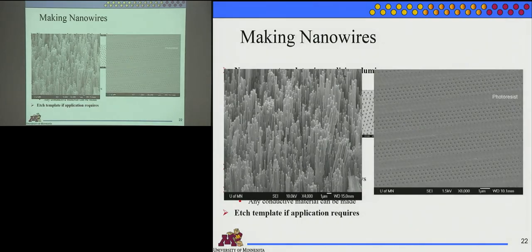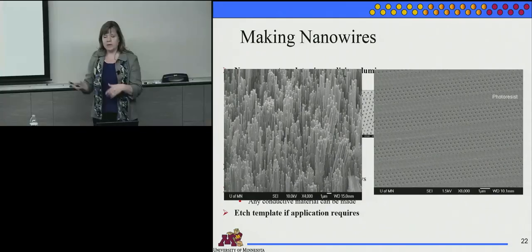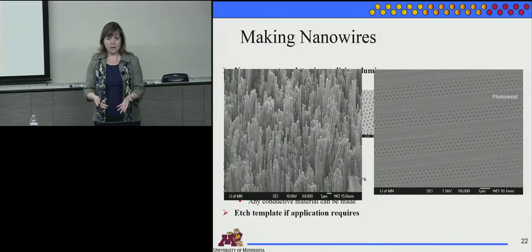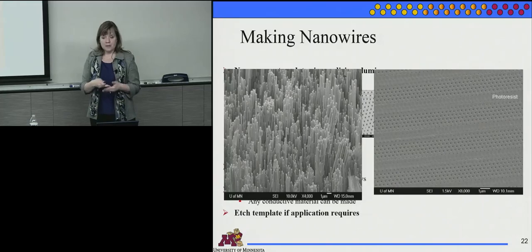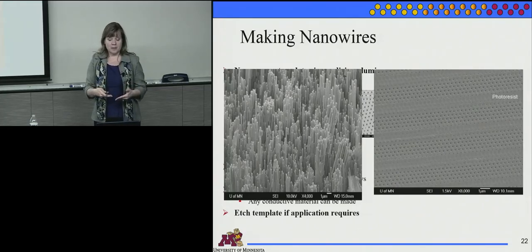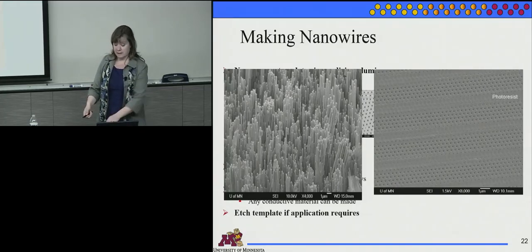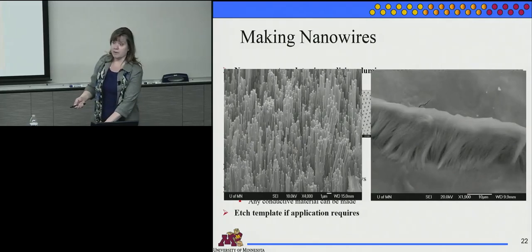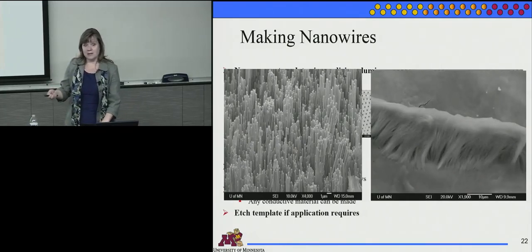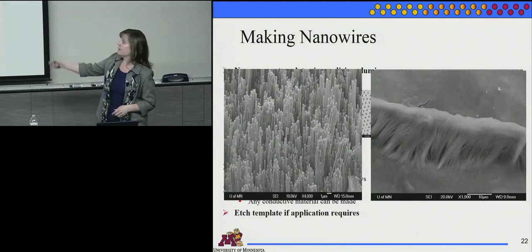And if you want, you can block off nanowires using the edge of an imprint. The one I showed you wasn't so sharp, but this one was a very sharp one. So we lined up photoresist with an optical microscope. You can't see nanostructures, but you line up the edge with the optical microscope. That lines up your lines of photoresist, and you end up growing rows of wires, which is very convenient for a lot of applications like MRAM and maybe even hard drive heads and so on.